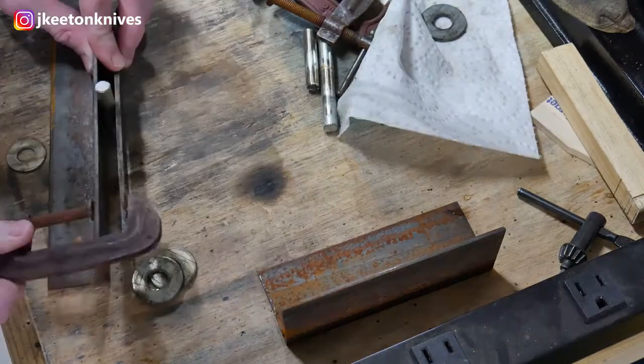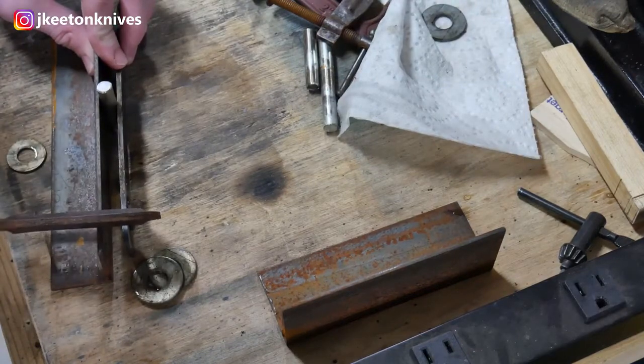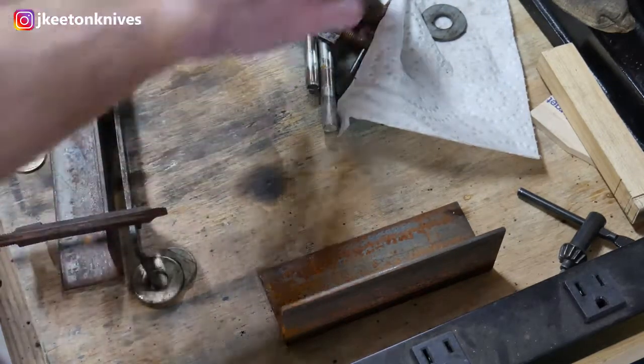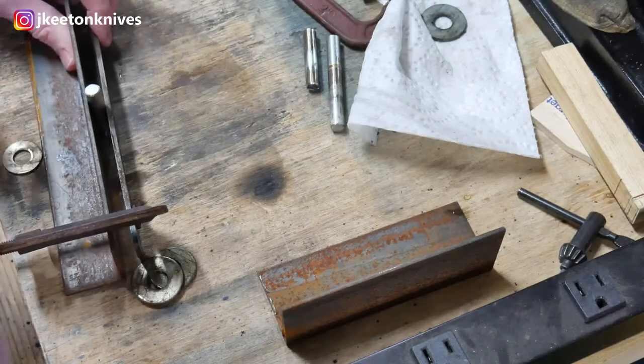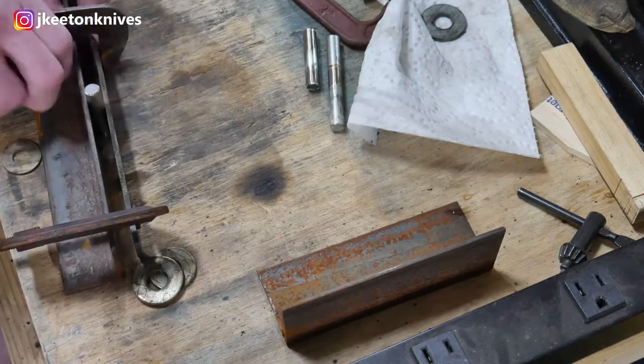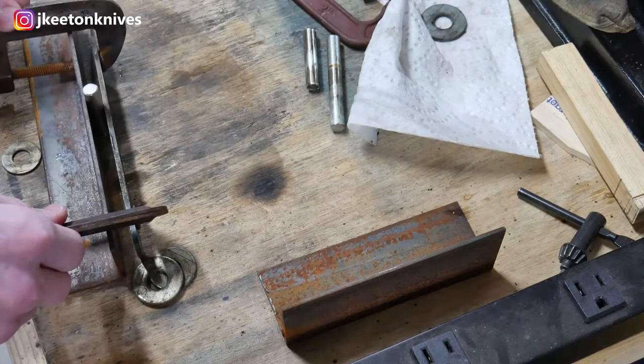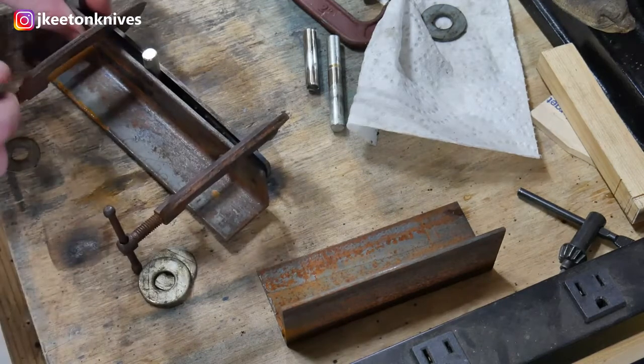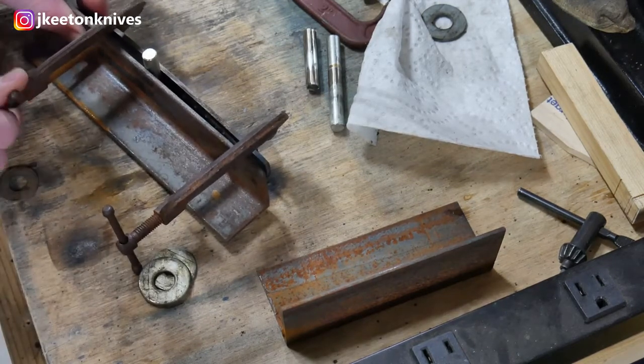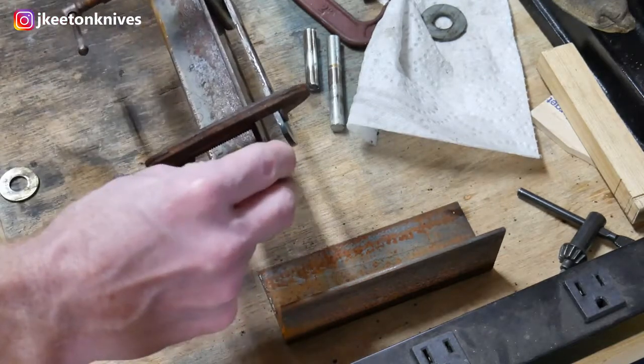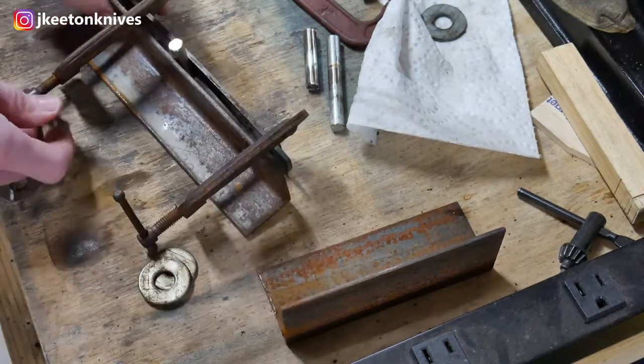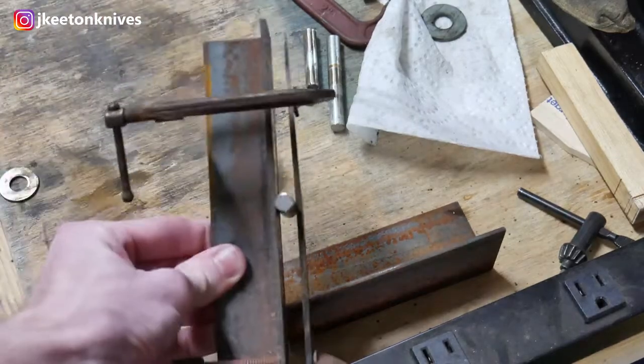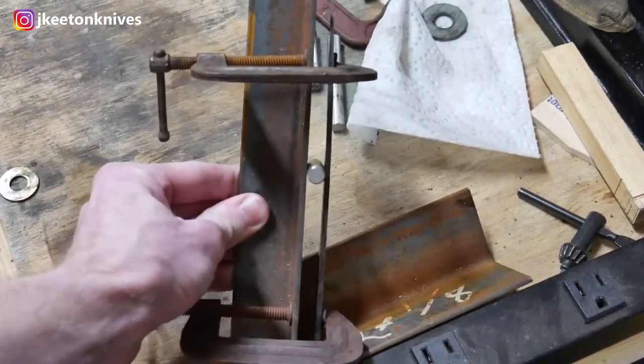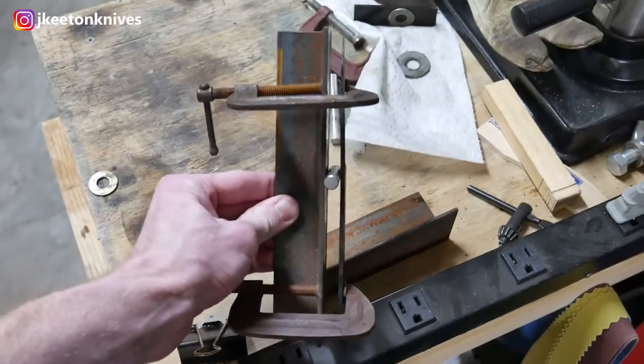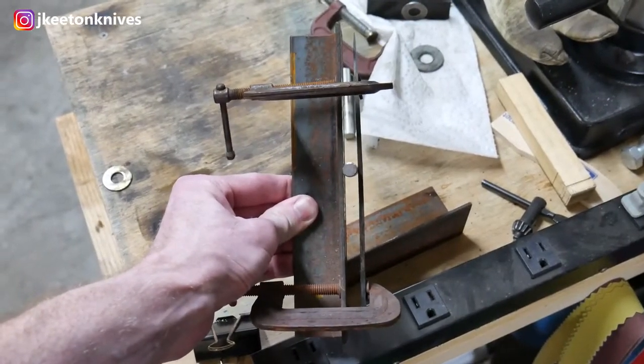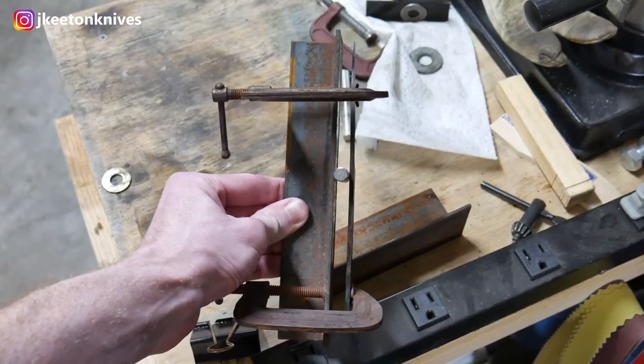But anyway, we take some C-clamps here and we get it clamped up, bending in the opposite direction of the warp. I may have it with a total deflection from the center line of about 1/8 of an inch counter bend, and that seemed to work very well. Another slight spoiler alert here, this thing came out great. So anyway, I get it clamped up, and then we move on to the second tempering cycle at 213 degrees Celsius to make sure we get this blade in a tough, usable condition.